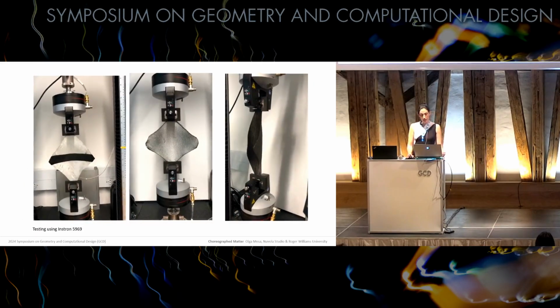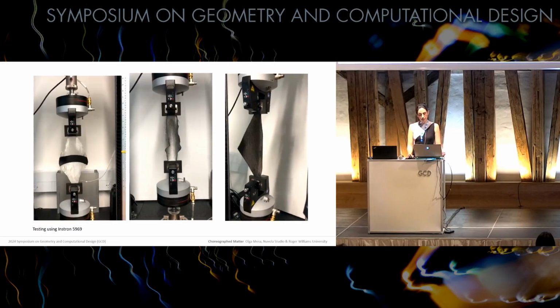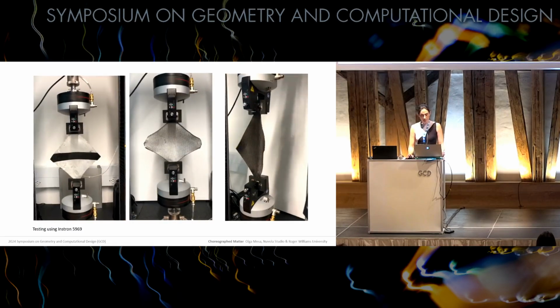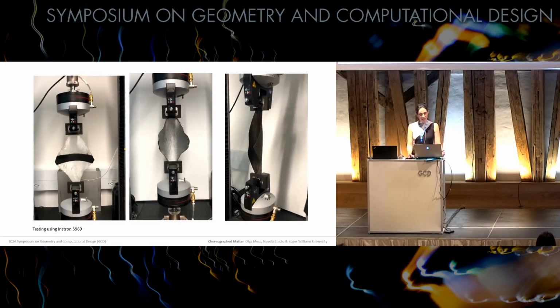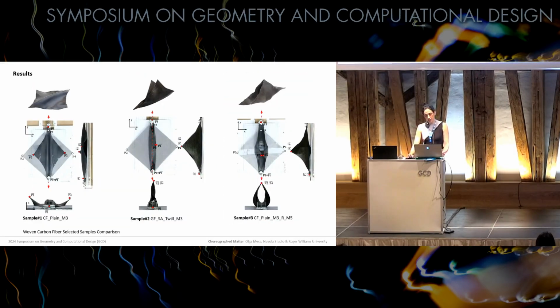Each sample was tested to determine behavior type, sample durability, actuation force, displacement of corners, and transition stages. Our results indicate that the intended behavior was achieved by either using a stiffer woven fabric or by adding central fiber reinforcement perpendicular to the axis of actuation. In this slide, samples 2 and 3 are showing the desired behavior, whereas 1 is deforming in that configuration by its own weight. All were infused in a silicone-based matrix.